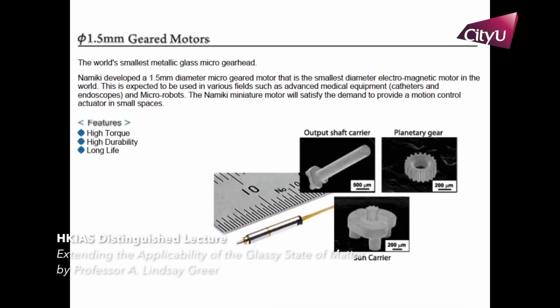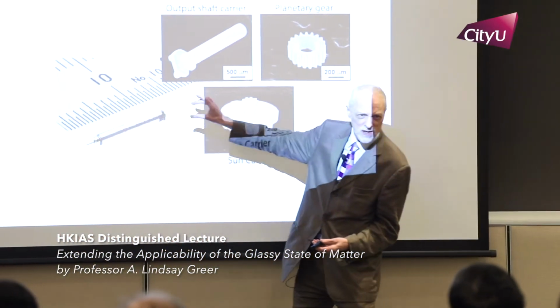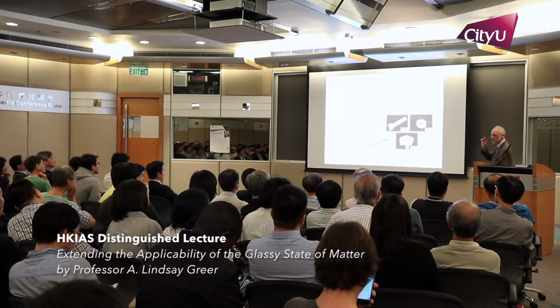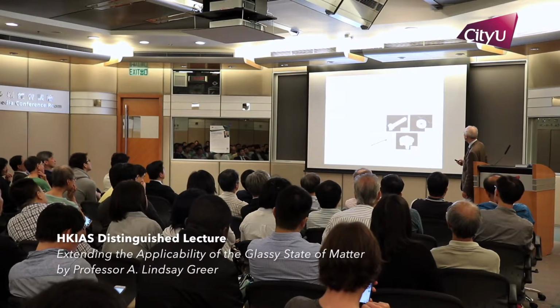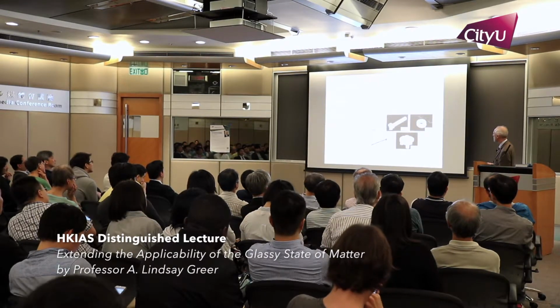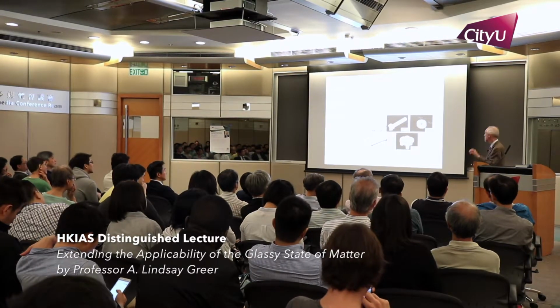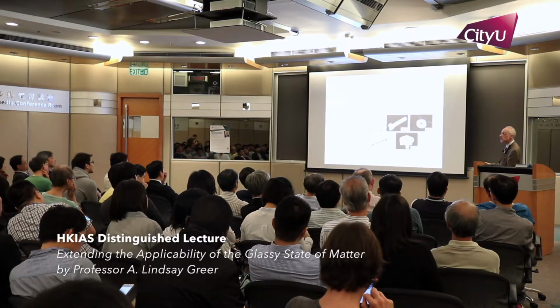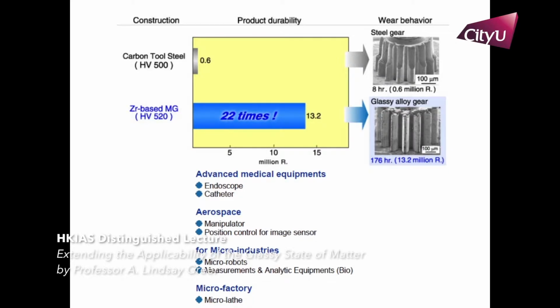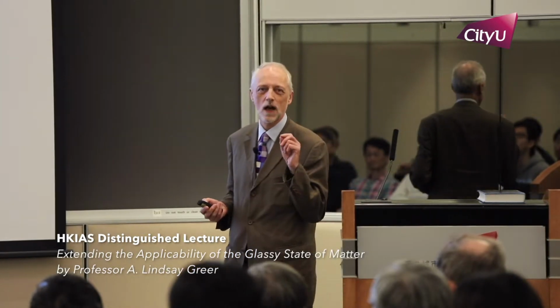This is just a little example from Japan. It's out of date. At the time when this slide was made, this was the world's smallest electric motor. So the external diameter, 1.5 millimeters. They now sell them with the external diameter of 0.9 millimeters. And inside the casing is a sun and planet gearing, so a central gear and planet gears around it. Those gears obviously have to be rather tiny, rather well molded. This compares carbon steel and its lifetime with the zirconium-based metallic glass and its lifetime as the gear. I think this is partly to do with the better mechanical properties of the glass and the better shape of the gear wheel. It can just be so precisely molded.